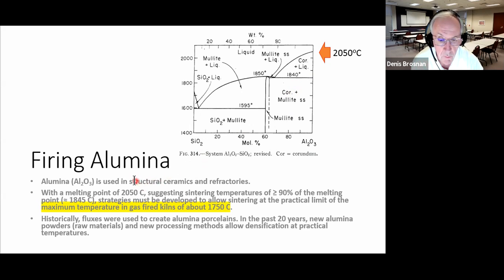So the melting point of alumina is way up here at 2050. And so if we would say that sintering temperature should be about 90% of the melting point, well, that's going to give us 1845 degrees C as the firing temperature for pure alumina, and that's impractical. It's just not going to happen in high production ceramic factories. So therefore, we have to engineer our products to get firing temperatures down to something practical, like 1750 degrees C, which can be achieved in a gas-fired furnace.